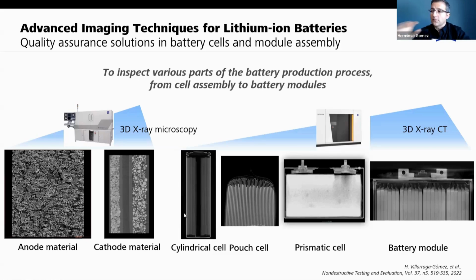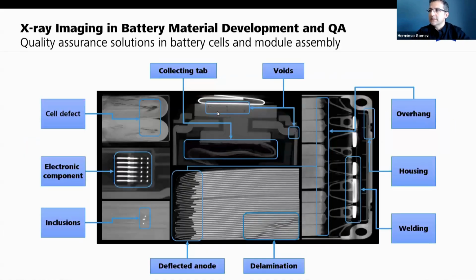So there are trade-offs. You can go to X-ray CT to penetrate through denser materials or thicker samples, but then you lose something in terms of resolution. So if you want to keep the resolution high, then maybe it's X-ray microscopy. And if you want to do the full chain, the process, then maybe you use both. You use X-ray microscopy and X-ray CT.